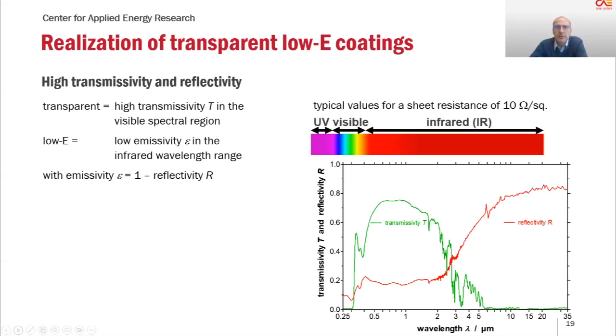And next, you see the wavelengths range from the ultraviolet spectral region over the visible towards the infrared region. And in this case, you see a typical silver nanowire coating with a high transmissivity of about 72%. Next, and low infrared emissivity of about 21%, which equals a high reflectivity in the infrared.